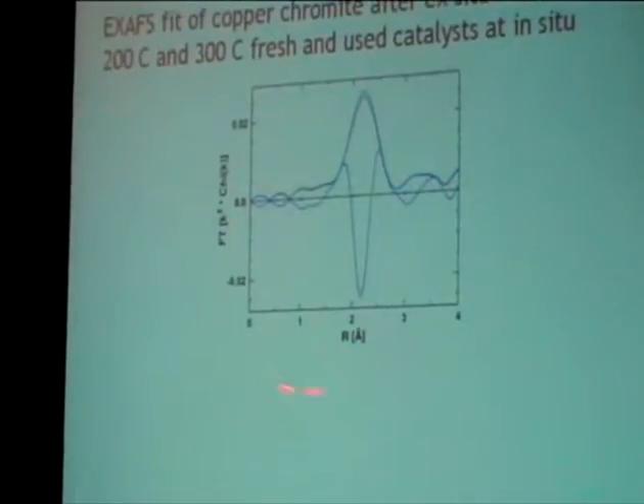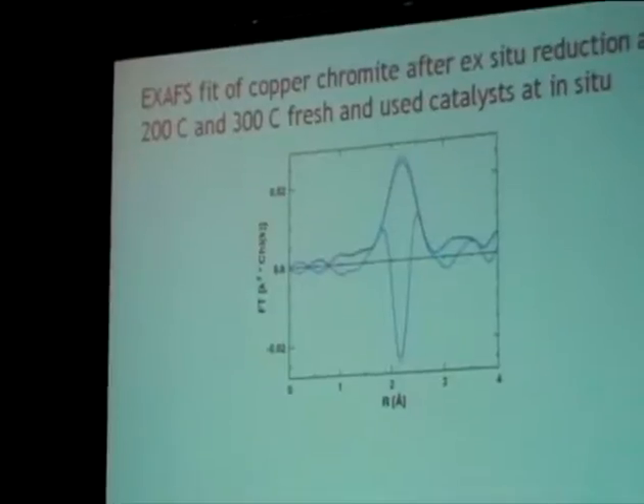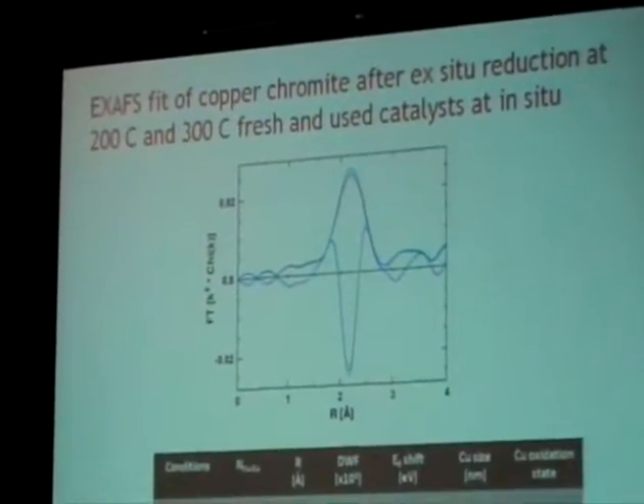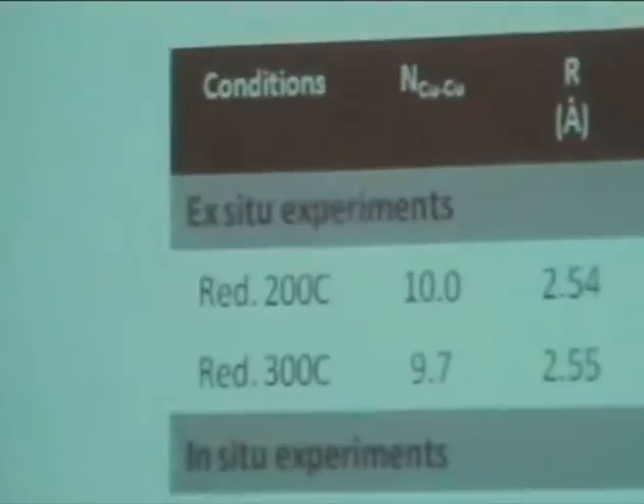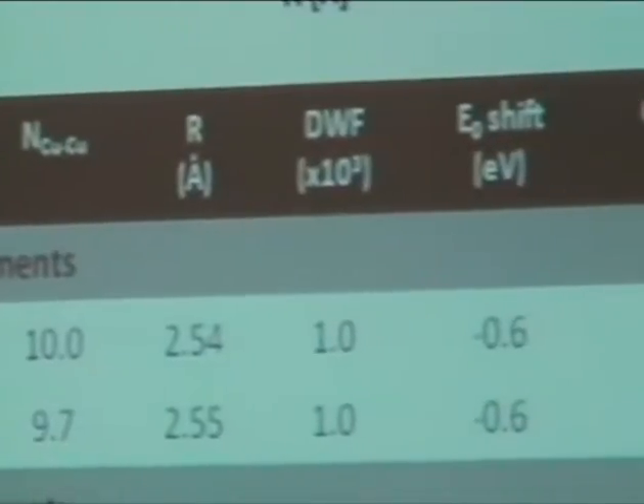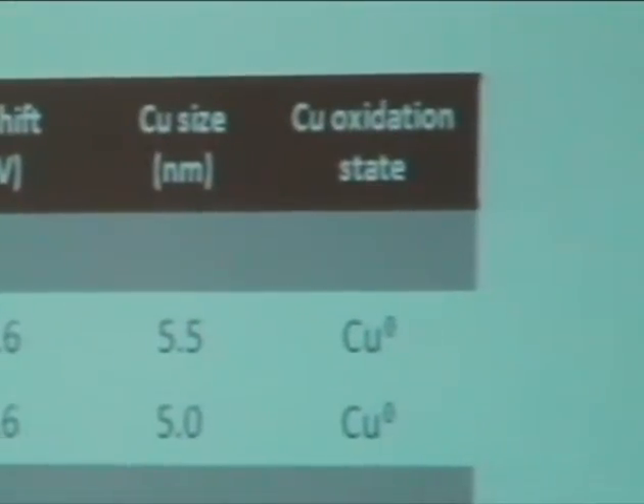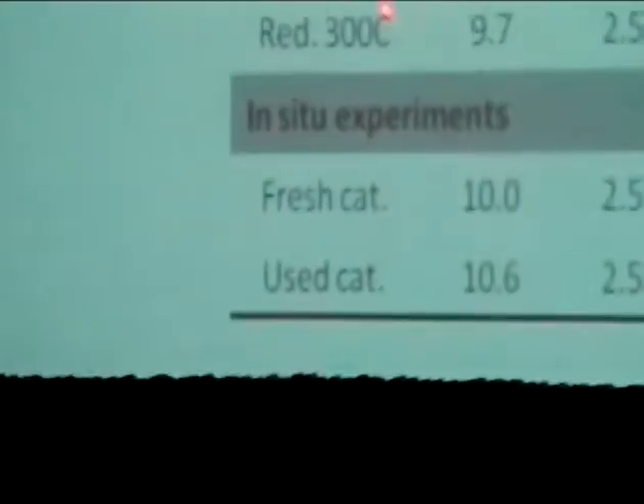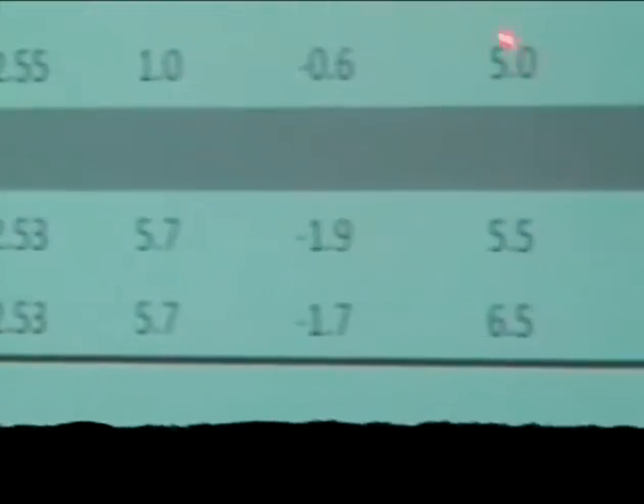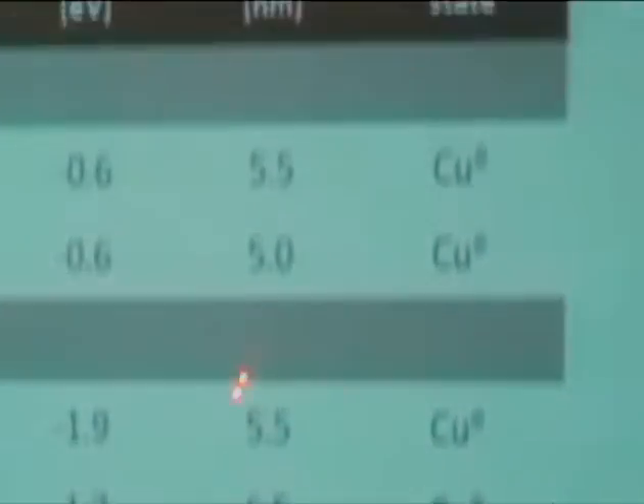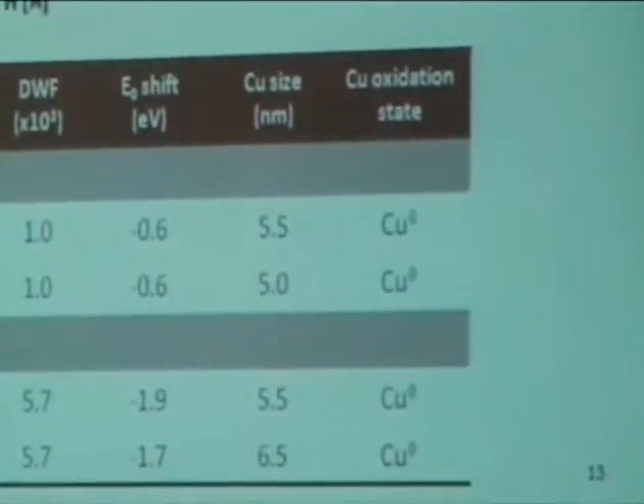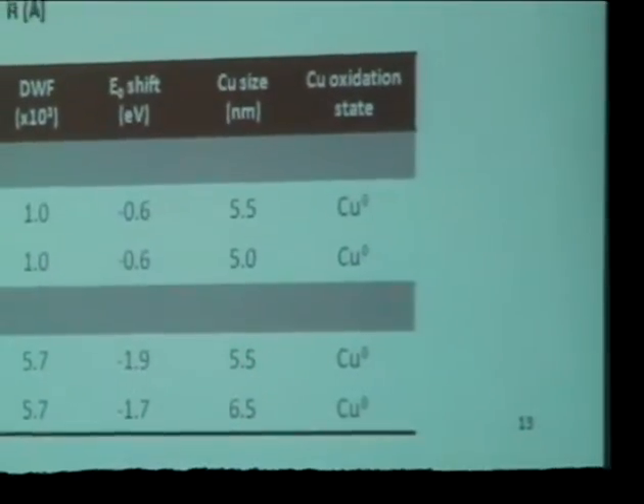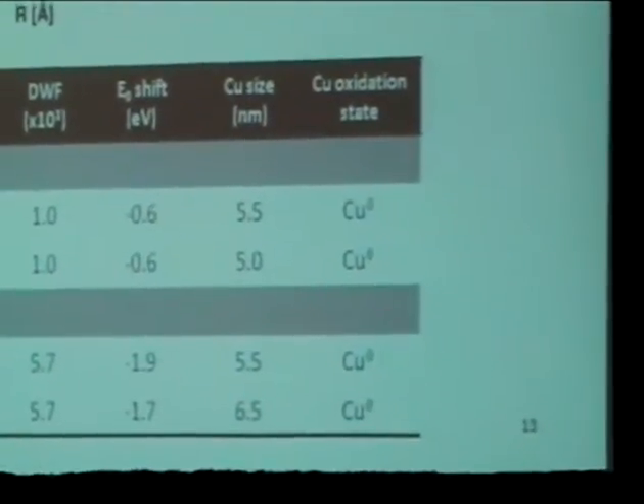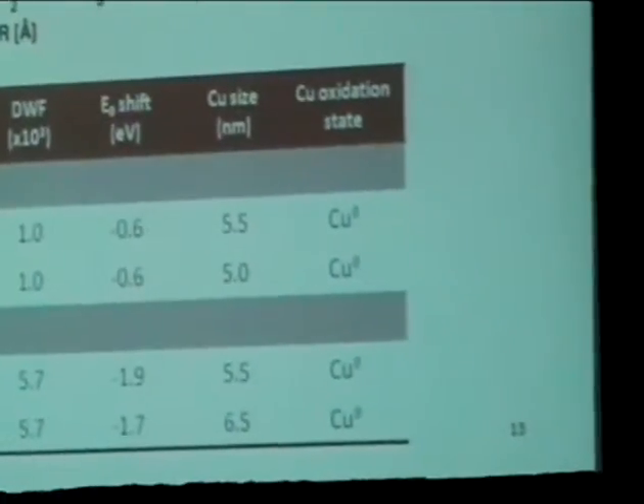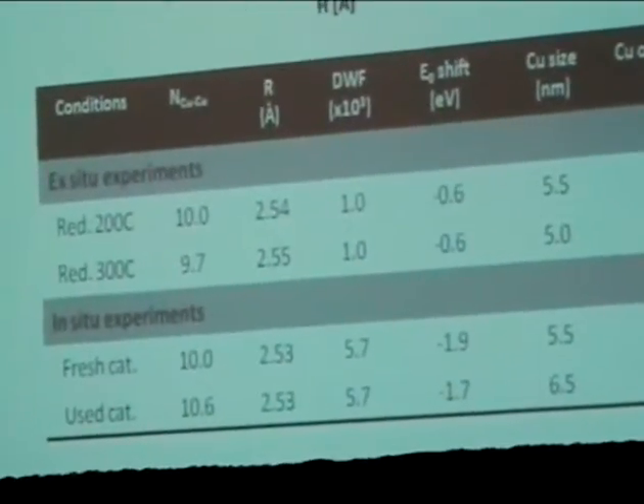Again, we use the real and imaginary portion of the EXAFS here to gain the information about the size of the particles and what they're bound to. What you can see is that in going from the starting material to the reduced state here, the copper crystallite sizes do not change very much. The fresh catalyst has an average copper size of about 5.5 nanometers. Under used conditions, it gets a little bit larger, but we don't feel that this is significant under these types of conditions.